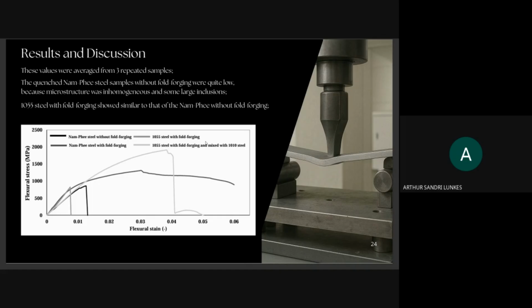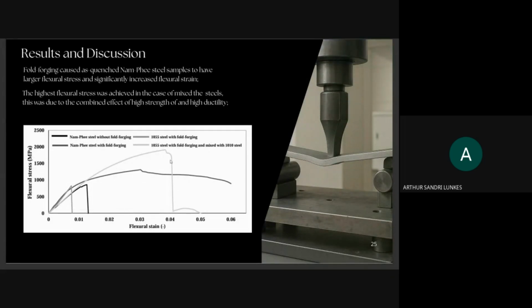The reason the Nam Phuc steel without forging is the lowest is because the mixture was inhomogeneous and had some large inclusions. That's the reason that the authors put in the article. So we could see that the fold forging process increased the flexural strain of the structure a lot. This one here is the Nam Phuc without the process, and this is the strain that the authors obtained with the process. We only multiply the flexural strain by around six times.